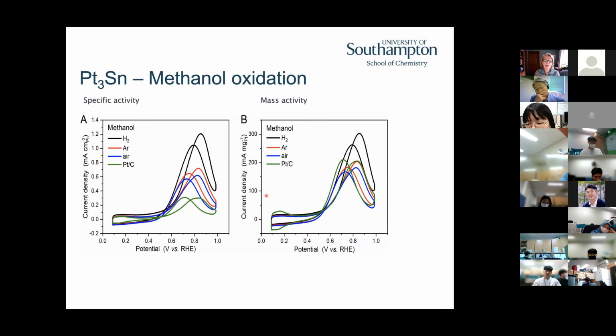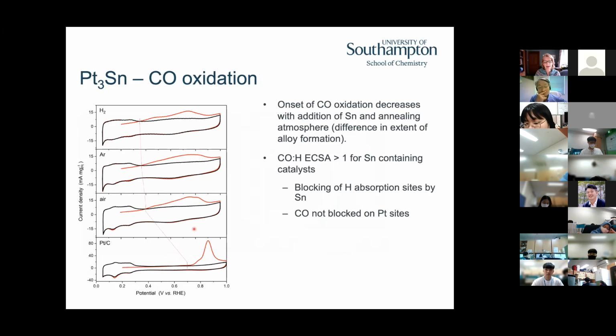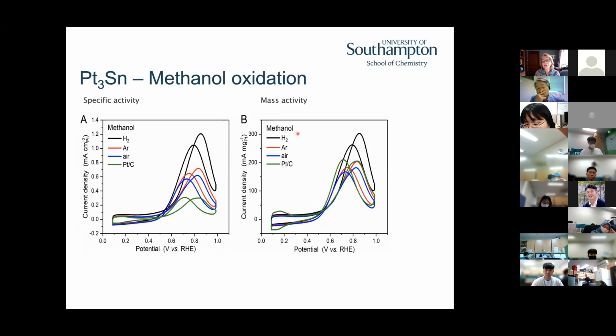It's interesting to look at these two plots though, because this one is the specific activity where I have normalized by the surface area of the platinum that's available, and that was done by measuring the area of the CO peaks, versus mass activity. So this is the fundamental activity of the material in terms of the catalysis. This is what it's going to cost you.